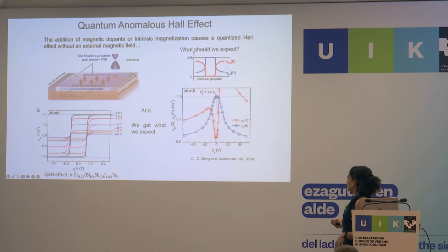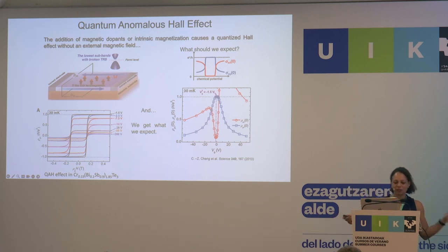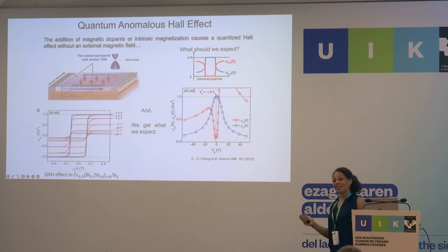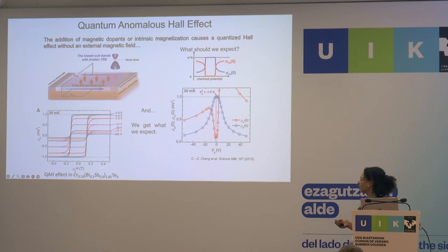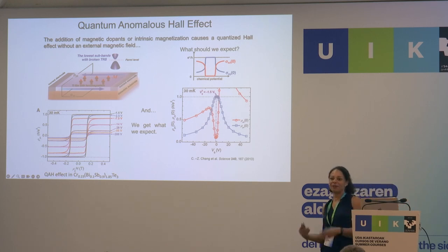But sometimes the very first experiments are not perfect, right? And so if there's enough convincing evidence in these experiments, which I think there is here by the approach to one and the drop towards zero, it can be really convincing anyway. This is not pertaining to any recent experiments you might have heard about in the news. But I do think it's worth noting, especially for theorists who look at the real experimental data and ask, why isn't this actually zero? That it's often materials issues, and you have to understand that if it basically follows the trends you expect, materials issues will be worked out within the coming years, as did happen in this case.